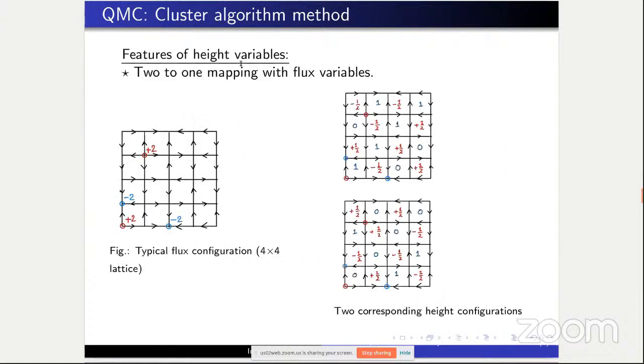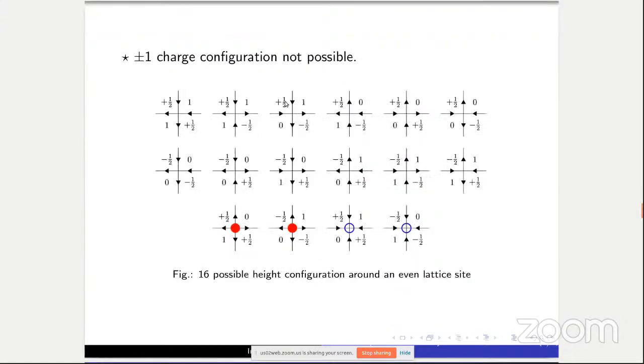The features of the height variables. There is a 2 to 1 mapping between these flux variables and height variables. So for a configuration in the flux variables, there are exactly 2 corresponding configurations in the height variables. Now these are the charge configurations in terms of the height variables. The first 2 rows are the charge 0 configurations. There are 12 charge 0 configurations in the language of the height variables, and these 2 are the plus 2 configurations, and these 2 are the minus 2 configurations. And note that the plus minus 1 charge configuration is not possible in terms of the height variables.